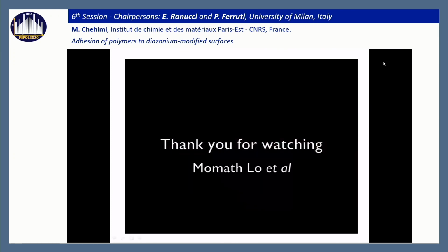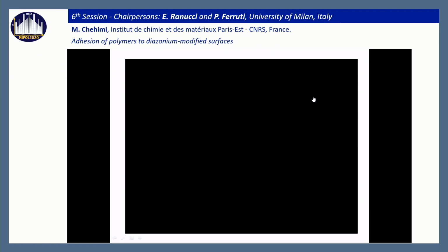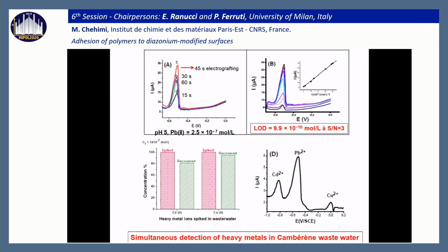Okay, so you see that we could remove the film on the diazonium-modified electrode only by scratching, no other ways. The adhesion was very, very strong. We made some electrochemical sensors. We tuned the adhesive layer for polypyrrole with the time of electroreduction of the diazonium salts, and we made some sensors which are very sensitive. We reached the nanomolar detection of lead.